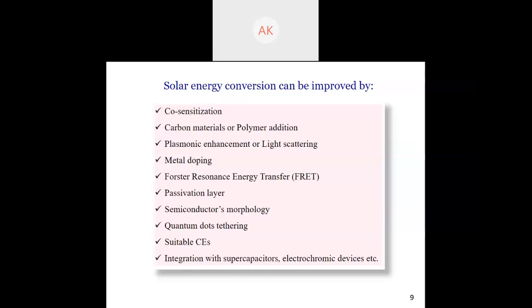There are materials which show FRET. You can use different passivation layers like ZnS, SiO2, amorphous TiO2. When you have a passivation layer, you can overcome a few recombination paths and therefore increase the solar energy conversion. Semiconductor morphology also plays an important role. If you have 1D structures like nanowires or nanorods, they are much better than nanosheets or nanospheres, which are 2D or 3D structures, as the case may be. Because in a 1D structure, you have unidirectional charge flow. Similarly, quantum dot tethering also plays an important role.